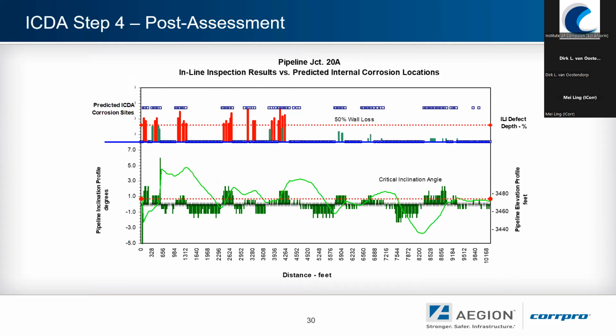This was a blind comparison between ILI results and ICDA results. Using the pipeline inclination profile and the flow modeling, it was possible to identify areas where water retention may have been an issue. When that was then compared, it matched up quite well with exactly where the ILI defects were identified. There were a certain number of ICDA sites that did not necessarily have resulting corrosion or had very minor corrosion, but the majority of the results lined up incredibly well.